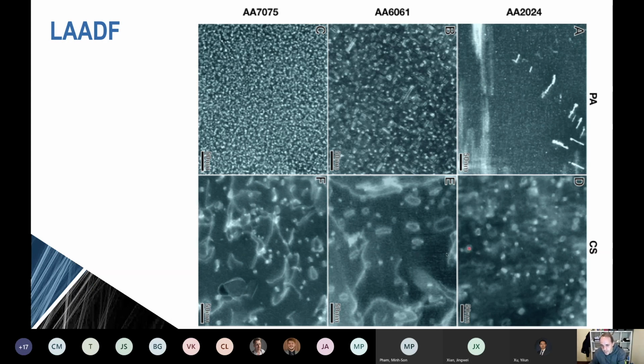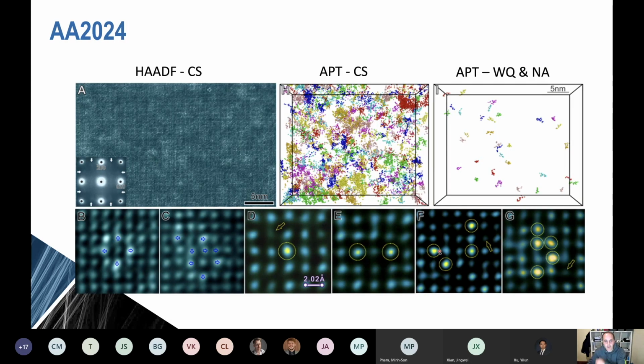In fact, you need to go in and look at much finer detail at the underlying microstructure. And actually, if you look at it in high-angle annular dark field imaging, you can see a very fine distribution of objects, sort of 2 to 3 nanometers in size. And in fact, we needed to go to atom probe to see it very clearly. And what you see here are 2 atom probe reconstructions.